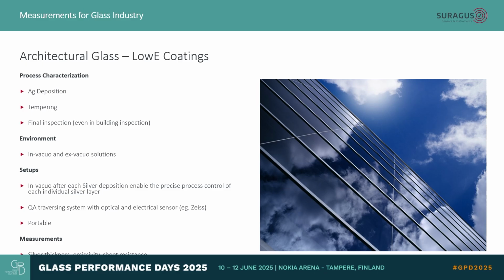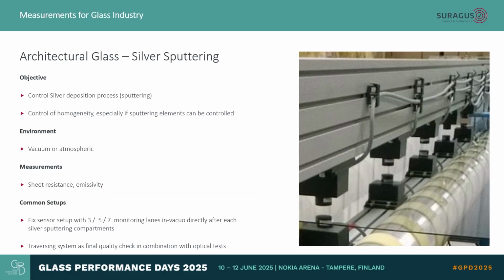This can be applied in vacuum or non-vacuum, but let's go to the silver sputtering as a process itself. Here the strategies are measuring directly after the deposition. There are different sputtering technologies where you can modify the sputtering homogeneity across the glass. Then it also makes sense to measure on different positions across the glass and to directly control the deposition process